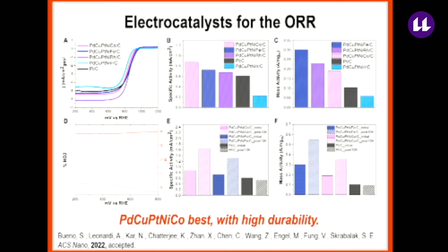So we've looked at them as catalysts as well. They're often better than platinum, but really their standout feature is, again, durability. And this is because they don't have much of a desire to demix. And so that helps to keep the non-noble metal components mixed and inhibits their leaching out in the highly corrosive environments of these electrocatalytic experiments.